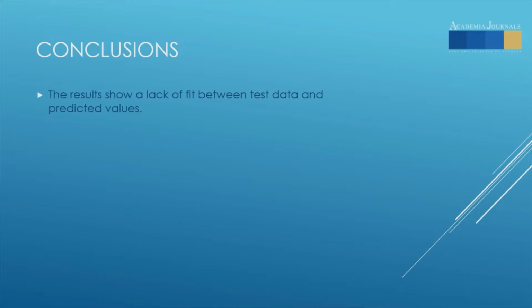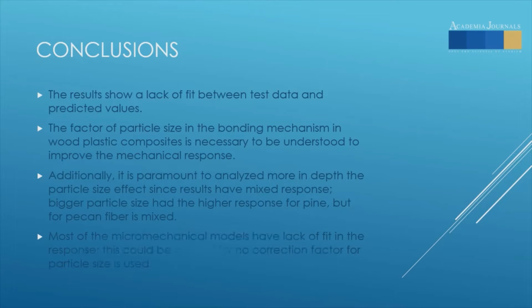Our conclusions are based on the following points. There is a lack of fit between test data and our predicted values from each of the micromechanical models. We see that the particle size factor in the bonding mechanism of the composite can be very important, and it is necessary to understand it better. It is paramount to analyze more in depth how particle size affects the response, since in this study we have mixed results.